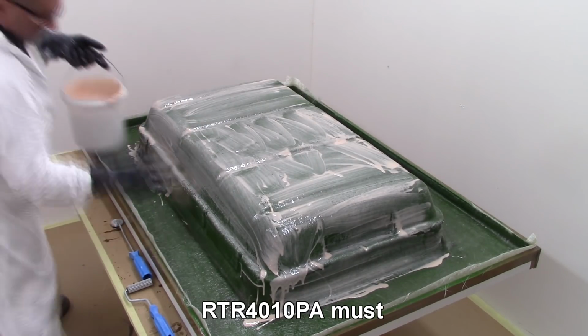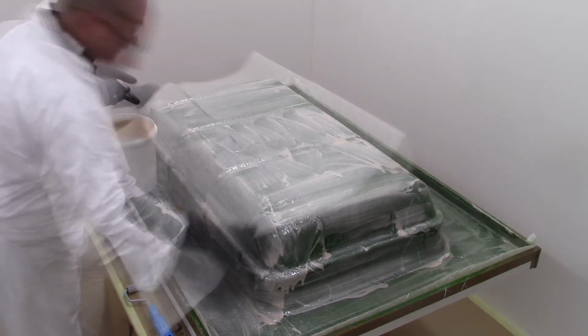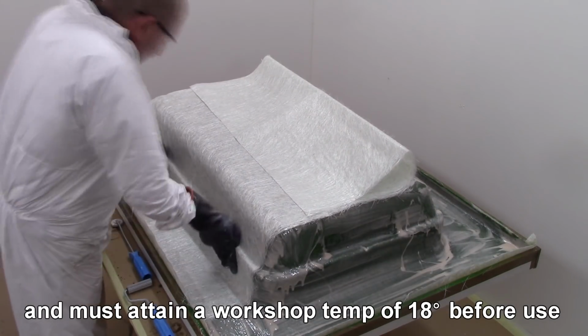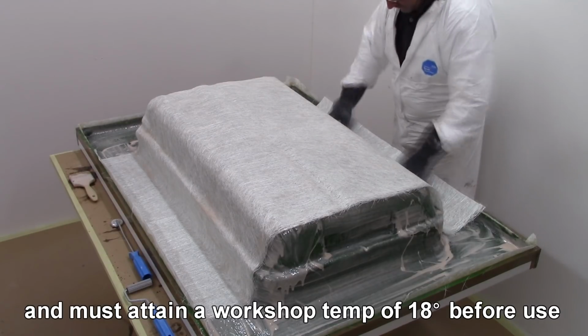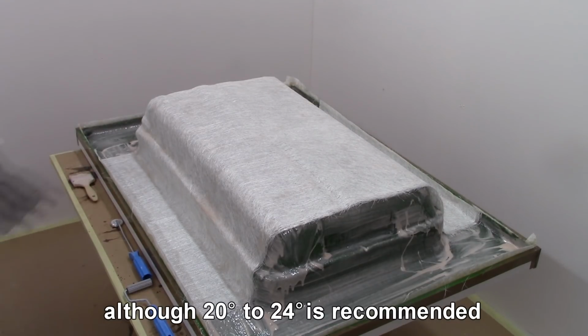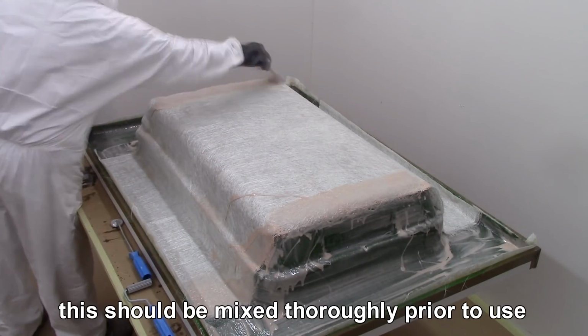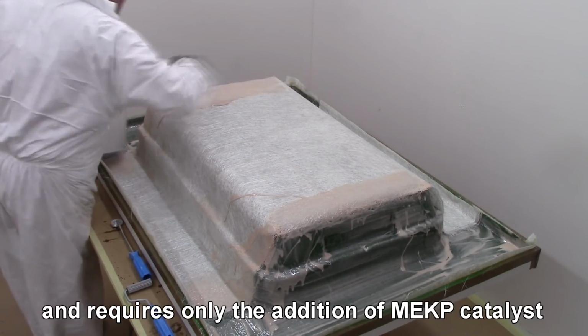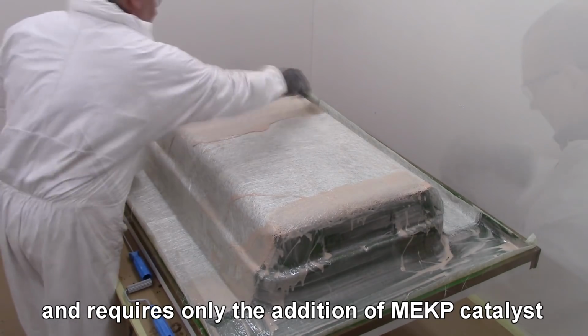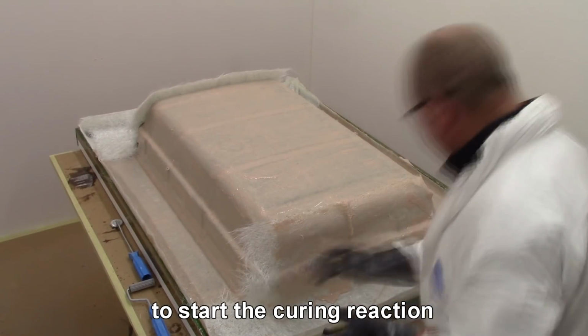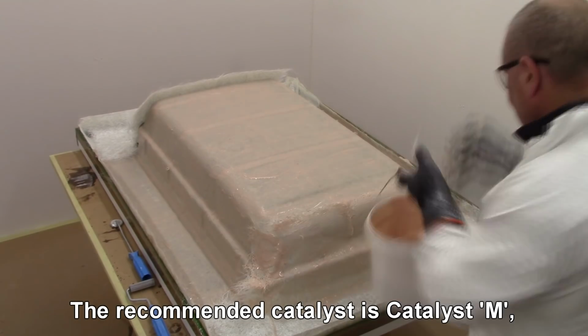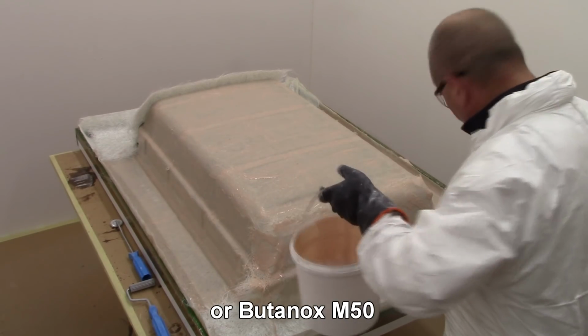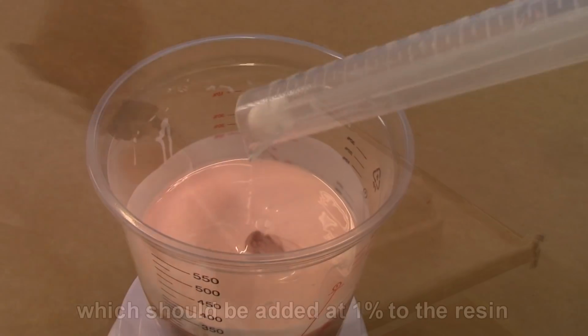RTR4010PA must be allowed to attain a minimum workshop temperature of 18 degrees before use, although 20 to 24 degrees is recommended. This should be mixed thoroughly prior to use and requires only the addition of MEKP catalyst to start the curing reaction. The recommended catalyst is Catalyst M or Butanox M50, which should be added at 1% into the resin and thoroughly dispersed.